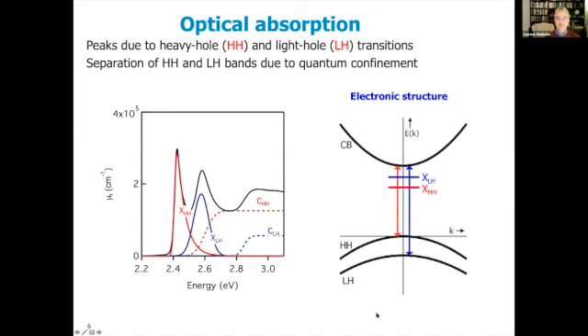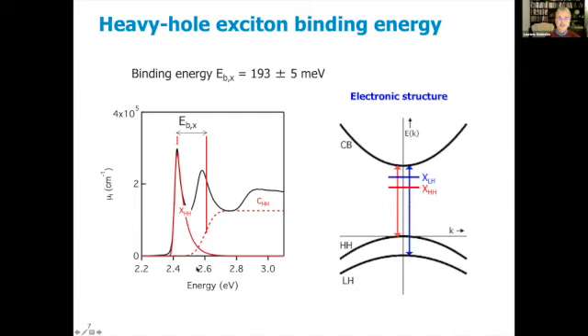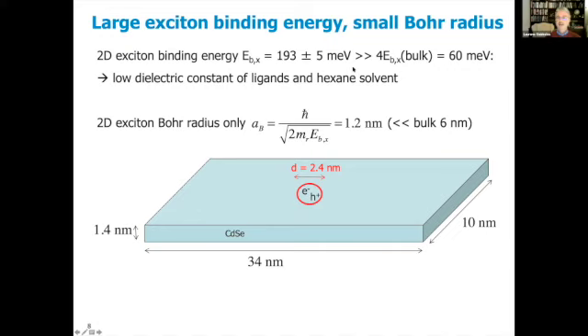you produce free charges. Now, we estimated the binding energy of an exciton, so that is the energy difference between the continuum, where you produce a hole in the heavy hole valence band and an electron in the conduction band, and this bound exciton level, by doing some phenomenological fit. And then we found a value of 193 millielectron volts. So that is almost 8 times kT. So excitons really have a high binding energy.